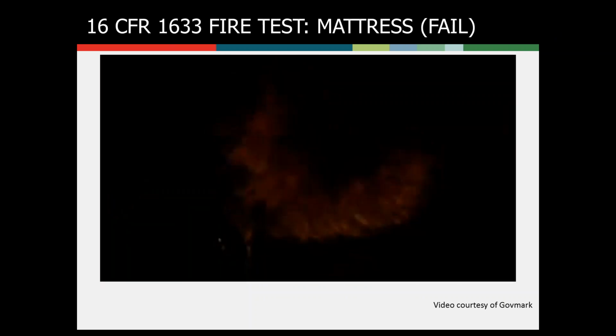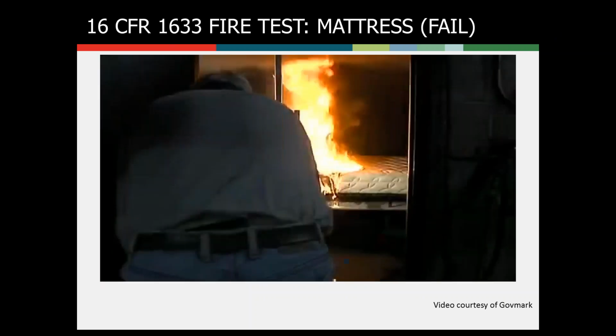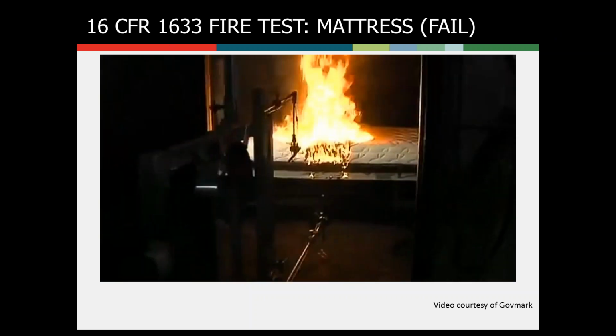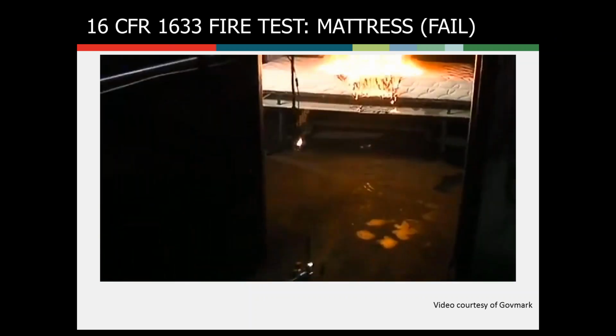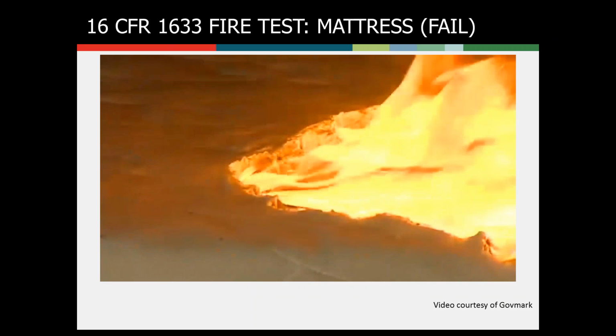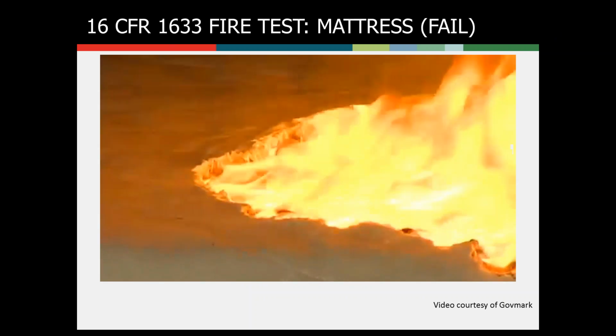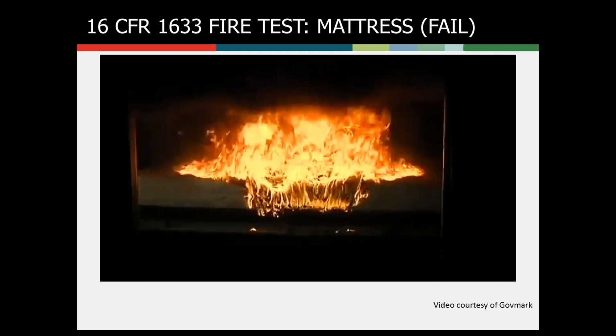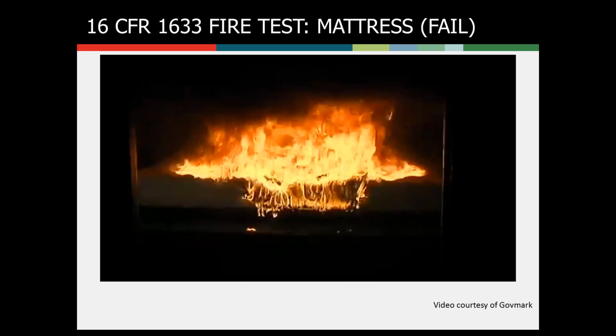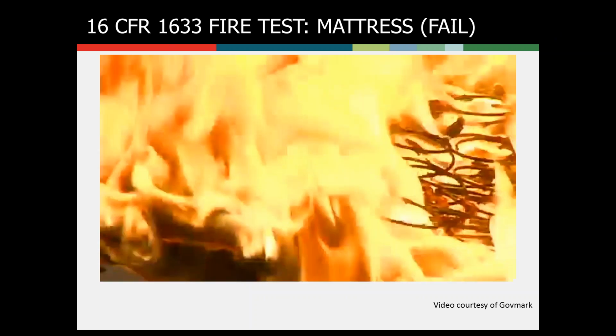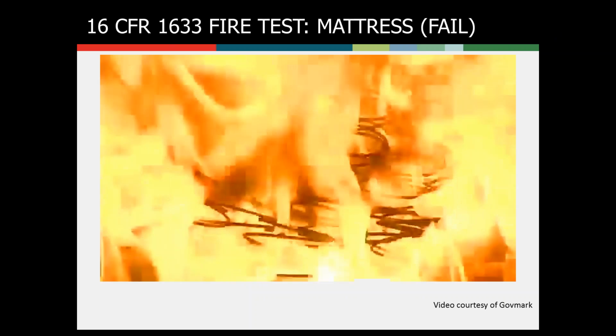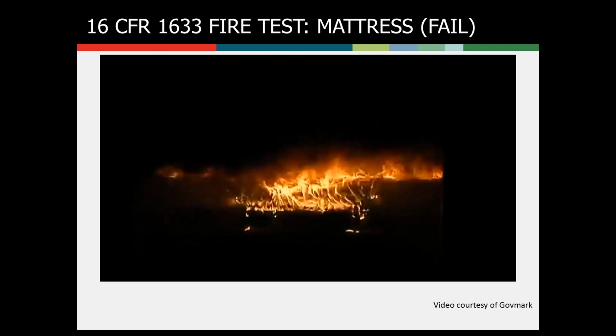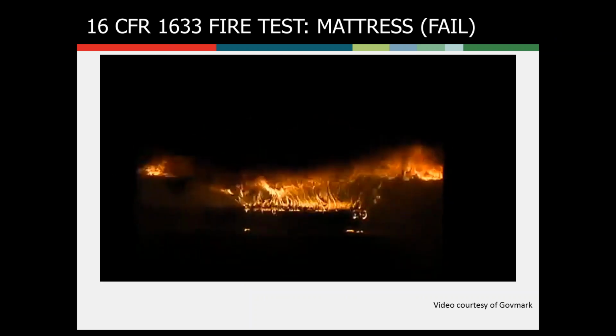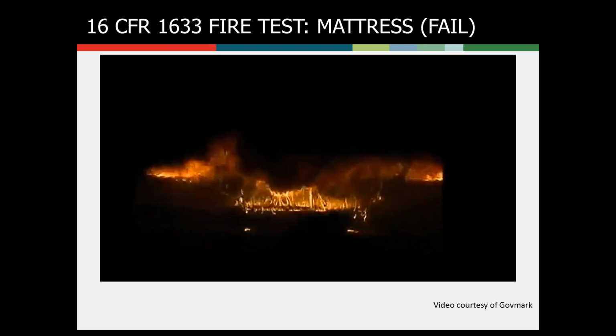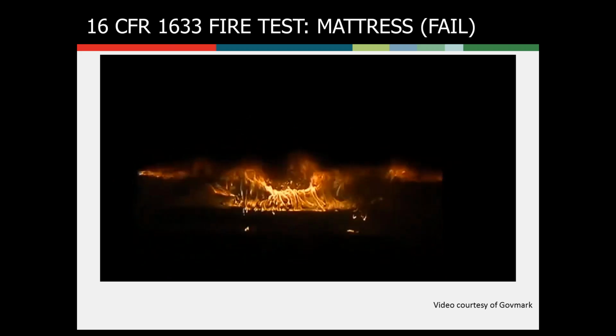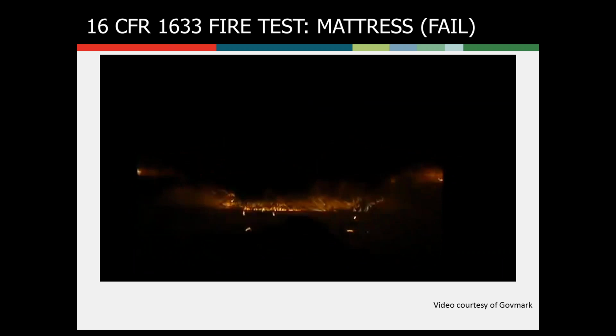It has a pair of T-shaped burners, one placed on top, one placed on the side, and it's representing burning bedclothes that you would anticipate, a fire originating on top of the mattress and burning. So the top burner is kept on for 70 seconds. The side burner is shorter duration, 50 seconds. After that time, you remove the burners and you allow the mattress to continue to burn for a 30-minute test duration. So in this case, this mattress has not performed very well.